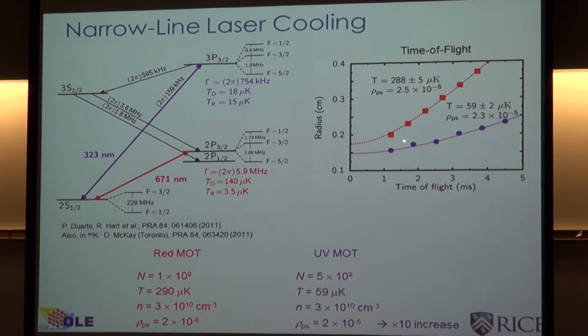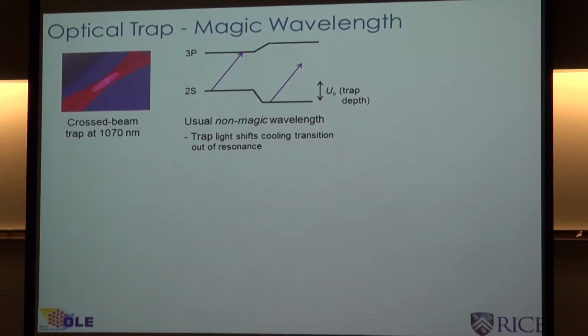So in fact, we did the experiment. We made a 323 nanometer source. Actually, we bought one. And we were able to get the temperatures down to 60 microkelvin, whereas our typical temperature with a red MOT is about 300 microkelvin. So that seems pretty good to us. It gave us a much better starting point. We ended up losing about half our atoms, but we increased the phase space density by about a factor of 10, to about 2 times 10 to the minus 5 in the MOT. If that was all there was, that would be mildly interesting, but it turned out it's even better than that.